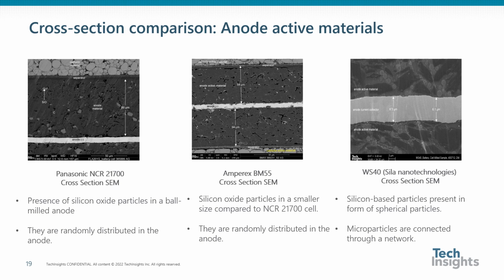These three pictures show the cross-section image of the anode electrode of Panasonic NCR21700, Amperex BM55, and WS40, the cell made by Sila Nanotechnologies. By comparing these images, we could track the evolution of the silicon-based technology for lithium-ion batteries. In Panasonic NCR21700, silicon particles are present in larger size than BM55. In WS40, the silicon exists in spherical microparticles, which is a breakthrough compared to the BM55 and NCR21700 cells. In BM55 and NCR21700, silicon is randomly distributed in the active material, suggesting a ball milling process. However, in WS40, the microparticles are connected through a network mainly made up of carbon. This figure shows that the silicon ratio is highest in WS40 compared to the NCR cell and BM55.